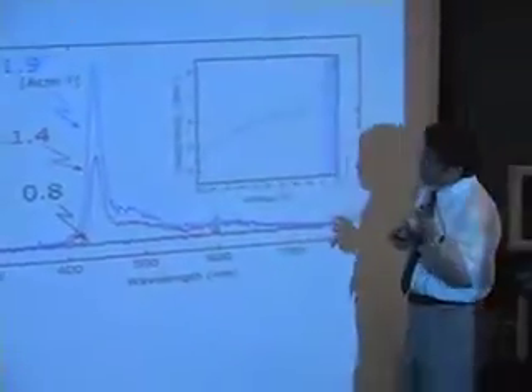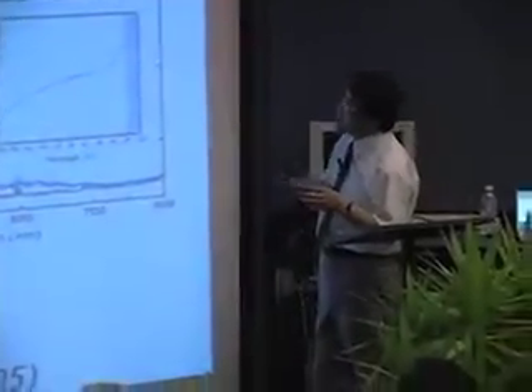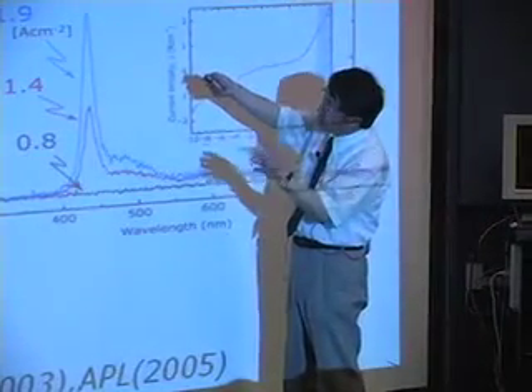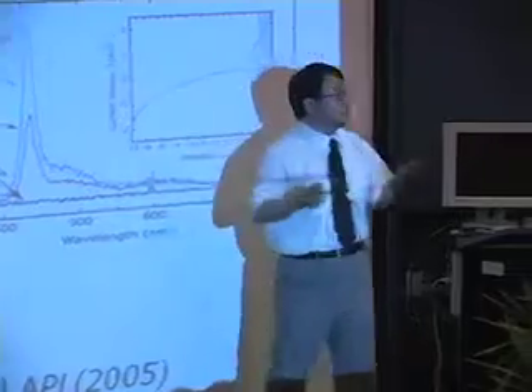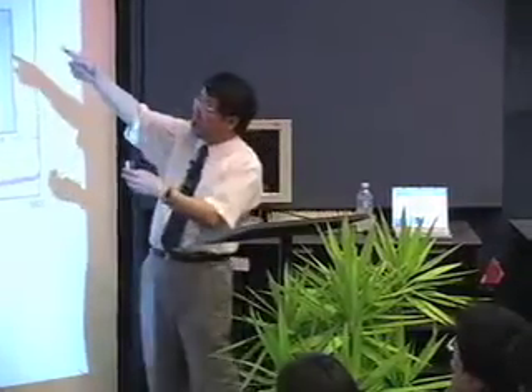So we replaced the copper 1-plus ion with a divalent transition metal cation, which meant we had to change the chalcogenide ion, 2-minus, with a pnictide ion, 3-minus. We checked the crystal structure, and within this framework we found that many materials had already been reported.